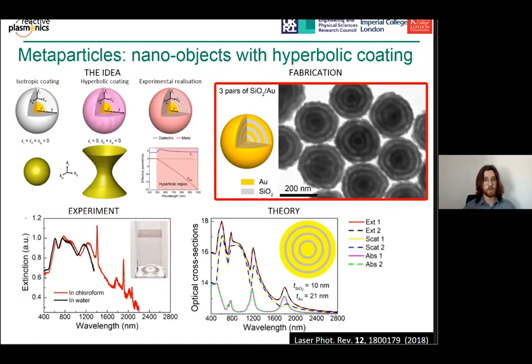Whereas typically, if we coat a material with an isotropic coating, we can change the sensitivity, but we're limited in the refractive index of these materials. Whereas the hyperbolic coatings give us essentially refractive index on demand. So we fabricated these onion-like structures. We can see them in TEM images here of alternating layers. And we see that we have this experimental observation of their optical response. We have this broadband excitation. And we can change the dimensions of the layers in order to tune these modes, these excitation modes, which will allow us to, again, access different wavelengths.